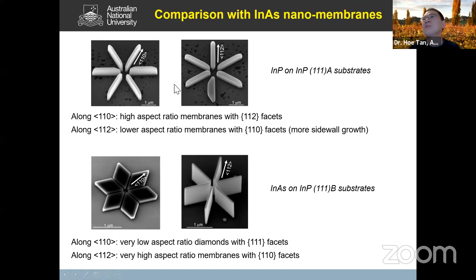So again, this depends on two things. One is the geometrical confinement, and the other is the surface energy. As I mentioned before, the width here is narrower because the side facet is a 112, whereas in this case, the side facet is a 110. So different facets have different surface energy. By exploiting the geometrical orientation and the surface energy of different crystal facets, we should be able to control the shape that we want to grow.